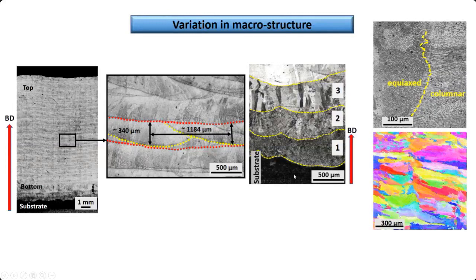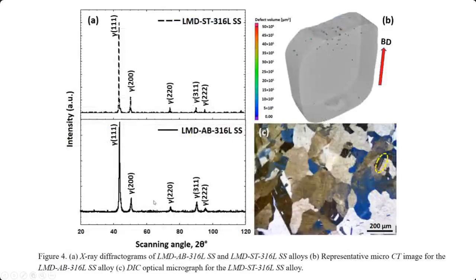This leads to different kinds of microstructures - equiaxed, columnar structure - and the interface often plays an influential role in dictating the properties of the materials as well. The layered structure is also evident, and the interface is very much evident from the EBSD structure itself.